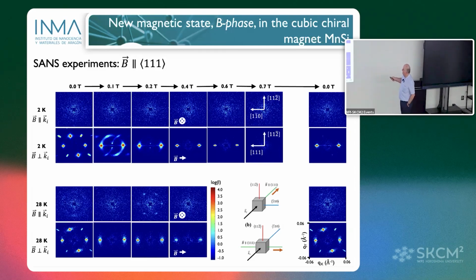And when you are going back from the ferromagnetic state to zero, for this configuration, you don't see anything, it's clear. But at the end, you end up with a single domain helix at ferromagnetic field here. At the very beginning, you have 4 domains. If you do this kind of hysteresis cycle, you end up with only 1.